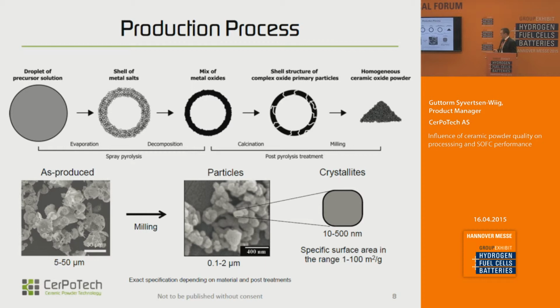So what does our powder look like? On the top here you can see what is actually happening inside the pyrolysis unit. You start with small droplets, some tens of micrometers in diameter. The water is evaporating, forming a shell of metal salts that partly decomposes into oxides through the furnace. For many of the materials, the time of flight inside the furnace at high temperature is not enough. So then we have a second step to remove organic residues and to form a single-phase material.